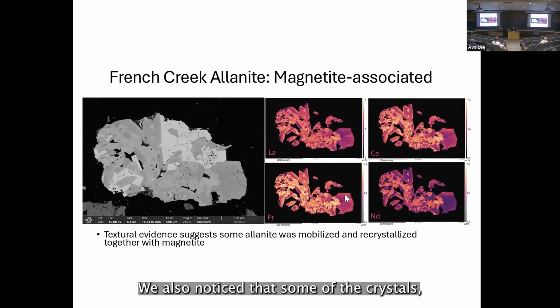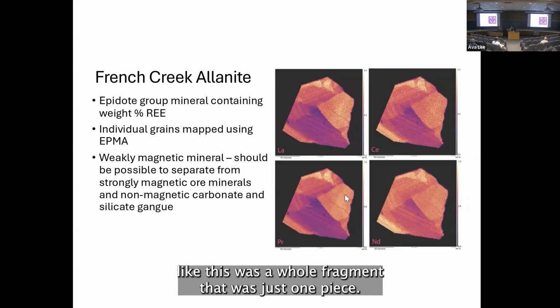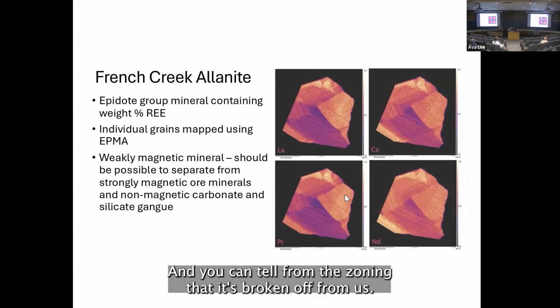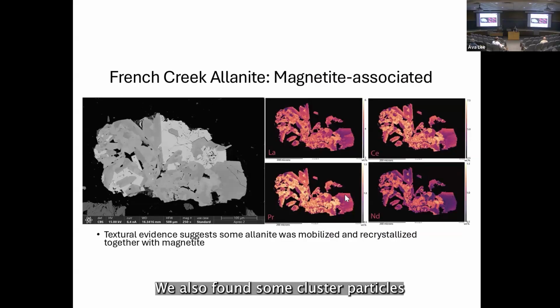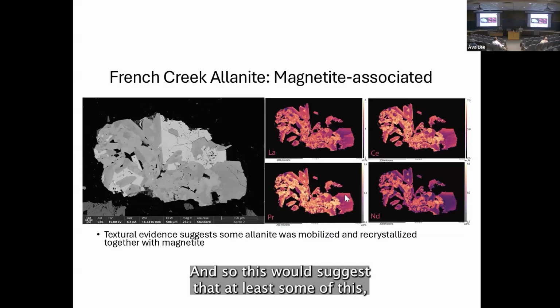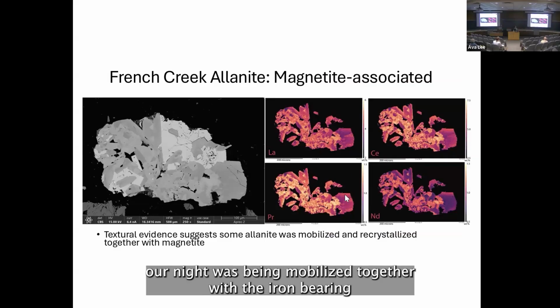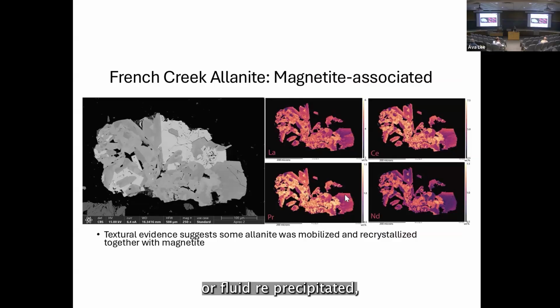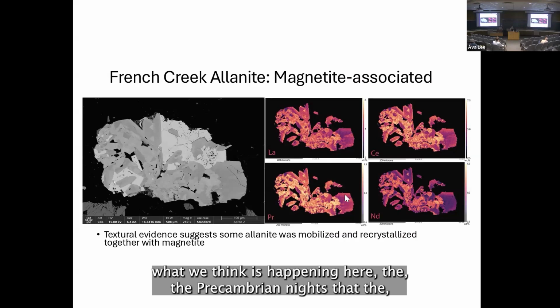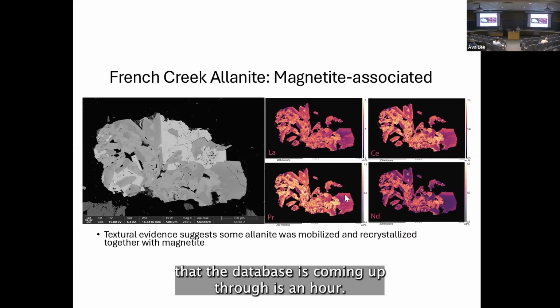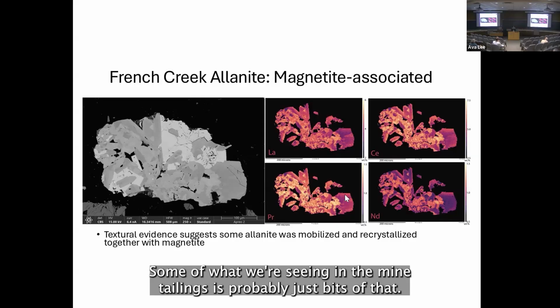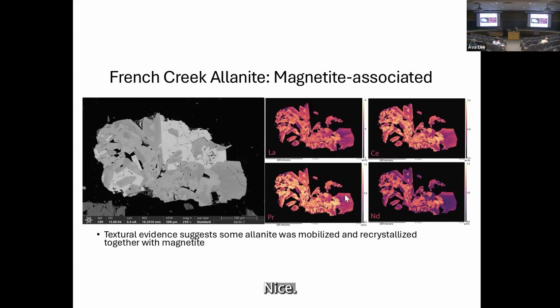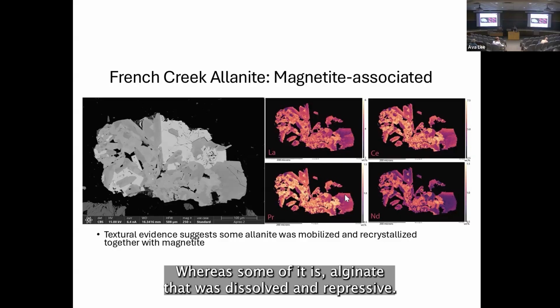We also noticed that some of the crystals, like this was a whole fragment that was just one piece, and you can tell from the zoning that it's broken off from a still larger allanite crystal. We also found some cluster particles that were magnetite and allanite co-precipitated. And so this would suggest that at least some of this allanite was being mobilized together with the iron-bearing ore fluid and reprecipitated. And what we think is happening here, the Precambrian gneiss that the diabase is coming up through is an allanite-bearing graphitic gneiss. Some of what we're seeing in the mine tailings is probably just bits of that gneiss, whereas some of it is allanite that was dissolved and reprecipitated.